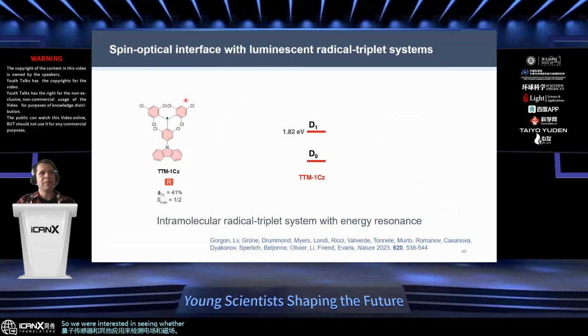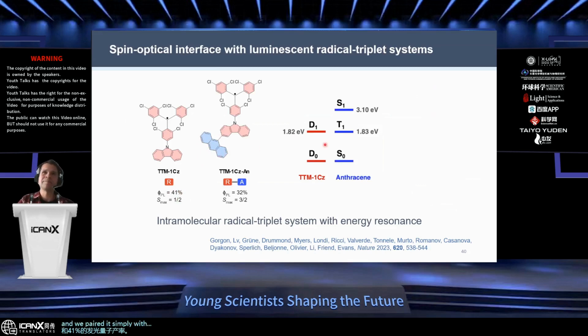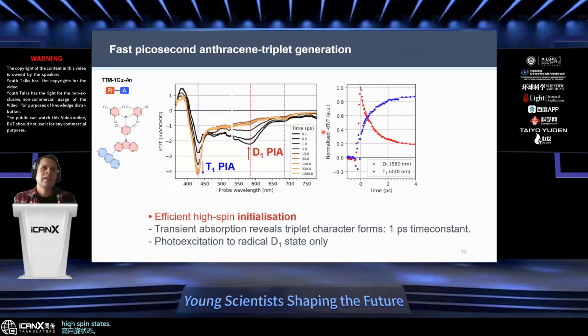So we were interested in seeing whether there were some opportunities to use our luminescent radical motif to improve some of the properties that you get from radical triplet systems. So we took our fruit fly molecule, which is TTM1CZ, which is a luminescent material with a spin doublet and 41% luminescence quantum yield, and we paired it simply with anthracene. And we chose this so that we could create energy resonance between the doublet exciton and the triplet exciton. We wanted to explore this potential for having equilibrium states and transfer between these high spin states. And what we noticed when we performed the transient absorption spectroscopy is that in this system, if you track the doublet exciton, it rapidly decays on the same time scale as a feature that we can attribute to the triplet exciton on the anthracene comes in.